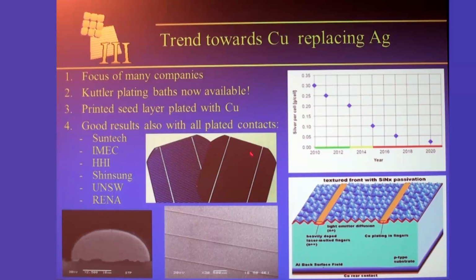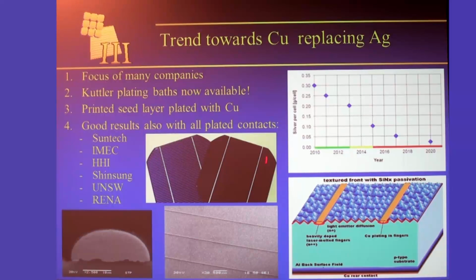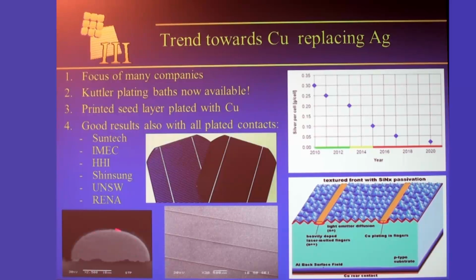And so this shows you a photograph of two solar cells. Here's one, a standard screen printed solar cell, where you can clearly see the screen printed metal lines. This cell, you'll notice, is much darker. The metal lines are there, you just can't see them because they're plated copper, and by using the technology developed at Suntech, these metal lines are very, very narrow, typically only 25 microns wide, each metal line. So too narrow for you to be able to see here. This shows you a magnification. So this is a cross-section of the copper. So there's 10 microns. So you can see that that width there is about 25 microns. And that's the aspect ratio they get when using these Kuttler plating baths. And then this shows you a magnified photograph of the top surface of the solar cell. So these are those very thin copper metal lines that you can't see here.